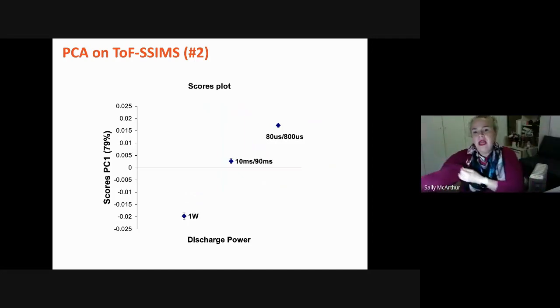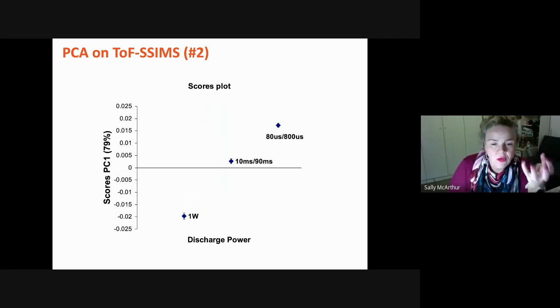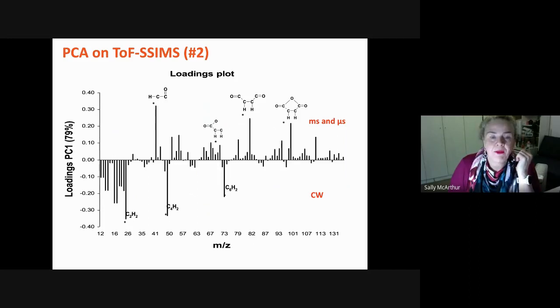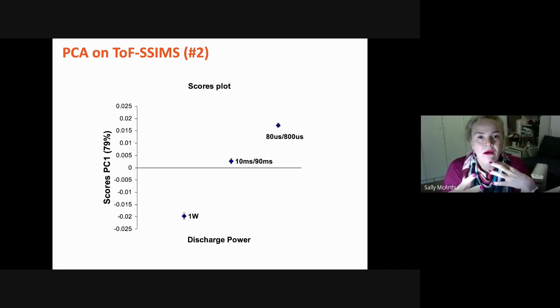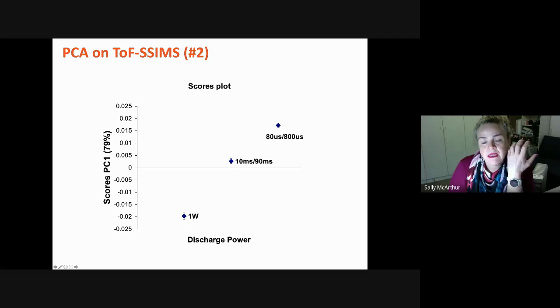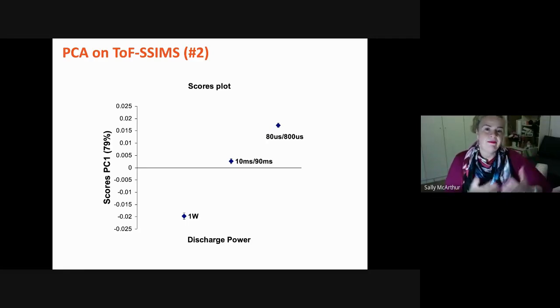The other thing I wanted to say, coming back to the point around the power question, is that we can use TOF-SIMS to actually separate and understand a bit better how our coatings are working. If we look at all of the data, we do a lot of principal component analysis, mainly because I come from the Dave Castner School of TOF-SIMS at University of Washington, and it's a great way of looking for what causes variation in your TOF-SIMS data rather than the huge complexity of peaks. But if you look at a scores plot where you compare spectra collected from the 1 watt to the millisecond pulsing and the microsecond pulsing, we could see from the XPS that they were different, but TOF-SIMS gives us the ability to say we can see chemical differences at the molecular level now, not just at the elemental or oxygen-containing species.